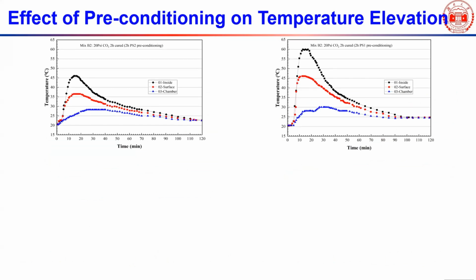Well, the other thing is, during carbon mineralization, as I mentioned earlier, it releases lots of heat. Because the clinker minerals were formed at 1,200, 1,500 degrees C, right? So basically, it has very, very high embodied energy. And so you can see here, the left figure is a temperature profile of the specimen at 3 locations.